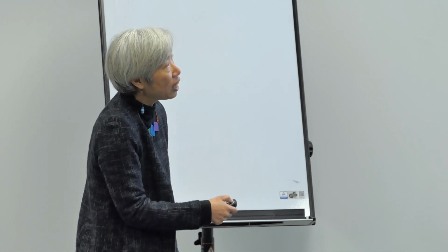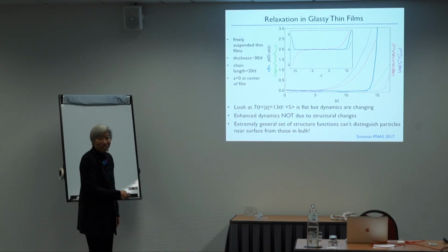What about softness? Softness is defined in a neighborhood, so if my neighborhood gets outside of the film, then that, of course, changes softness a lot. And that's what's happening here. But until I get to the point where my neighborhood gets outside of the film, it is flat. It's not changing. Softness does not depend on position in the film.